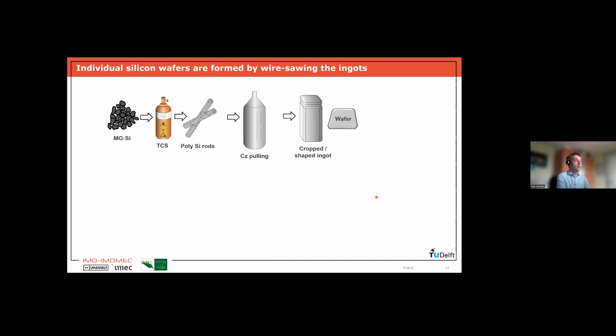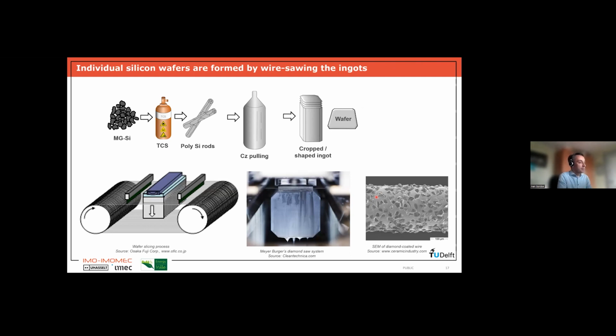So how are the wafers now made? Well, these blocks are actually cut into individual wafers by so-called wire sawing. So this is shown here. So these days, already for many years, the wires that are used are diamond-coated metal wires. So basically, you have very small diamond materials, which are actually what cut the silicon. And this wire is very long. It can be kilometers long. And you have special machines where these wires are actually in parallel cutting a whole ingot into individual wafers.